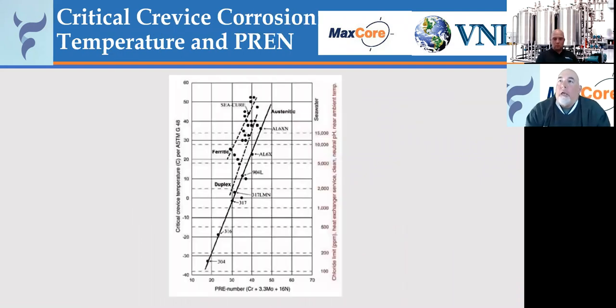Now, this particular chart actually shows the critical crevice corrosion temperature and the PREN number. It gives you an idea of the ranking of the materials as well. On the bottom axis, you see the PREN number calculation and where that actually falls on the graph. On the left-hand side is the critical crevice temperature that you might be seeing. And on the right-hand side is an indication of how much chloride, in parts per million, can be withstood at those particular levels. So it's a chart that can point you in the right direction when it comes to material selection. And that's what we're really looking at when you get right down to it in these corrosive applications. So that leads us into proper material selection and how and why we do it.